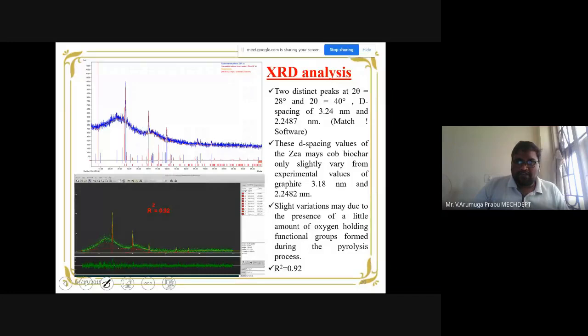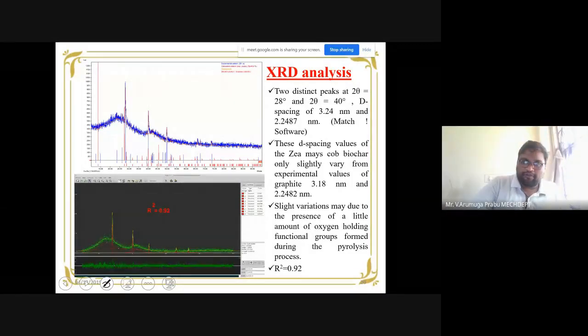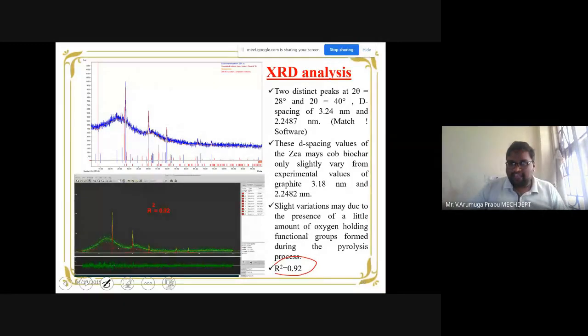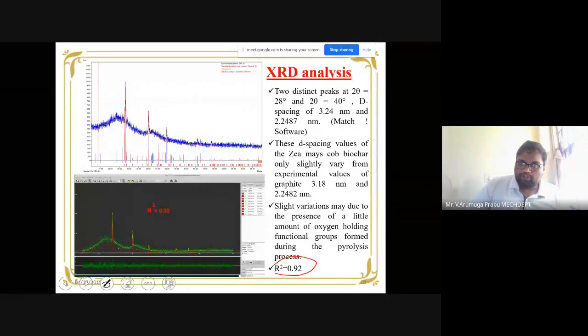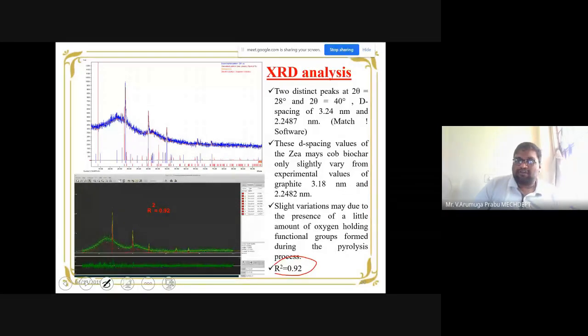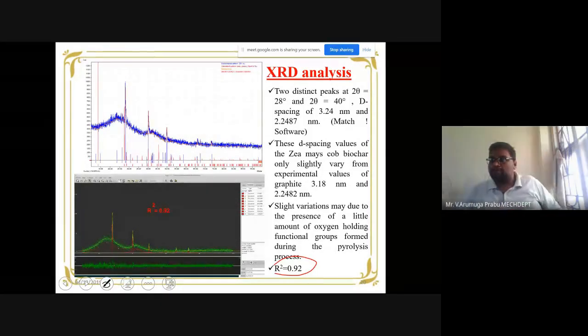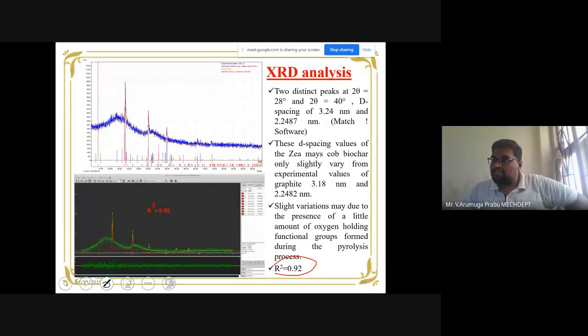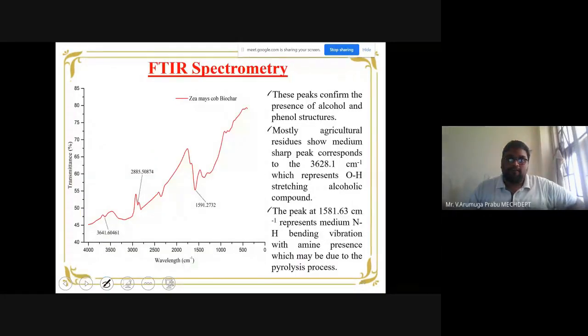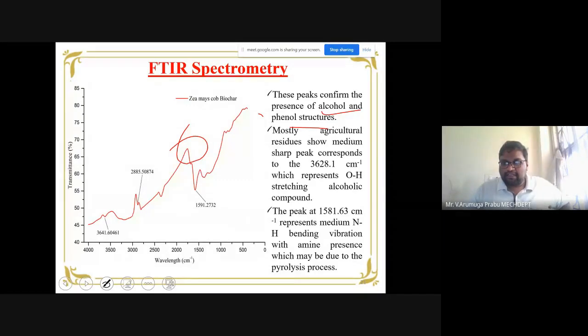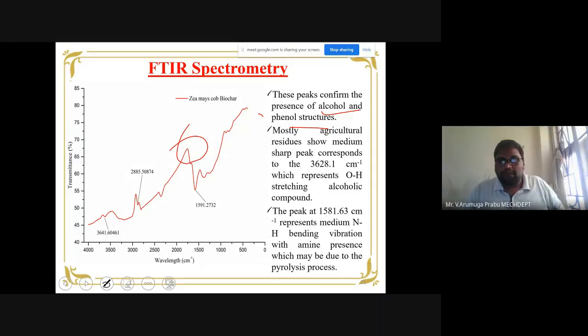And this is the XRD analysis that we carried out, and by means of the XRD value we got, we are in a position to ensure the presence of high carbon. So to ensure the presence of high carbon, we carry out this XRD analysis as well as the FTIR test, sorry. Okay, then these are the FTIR results. Here also the peaks show the presence of alcohol and phenol structures. All these tests are to confirm that more carbon content is present in the biochar.